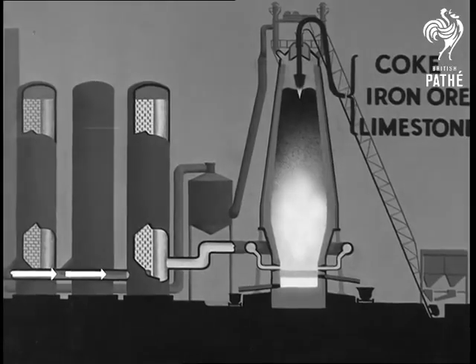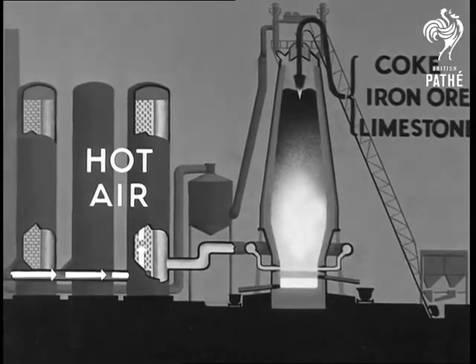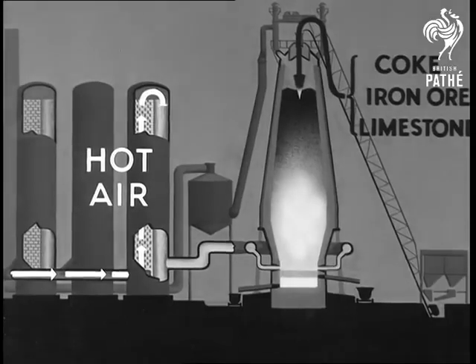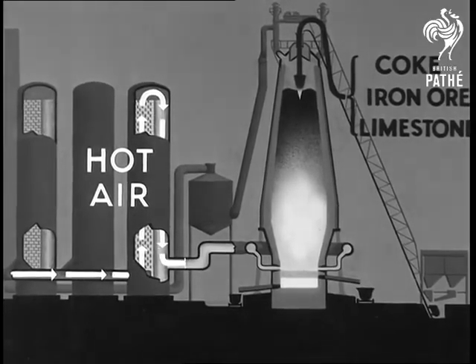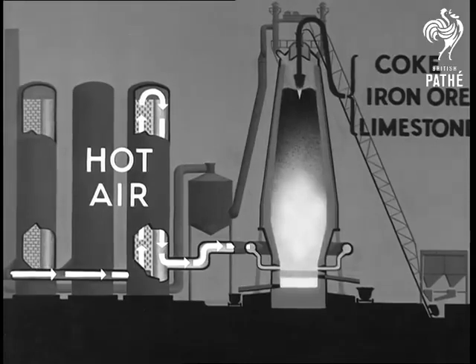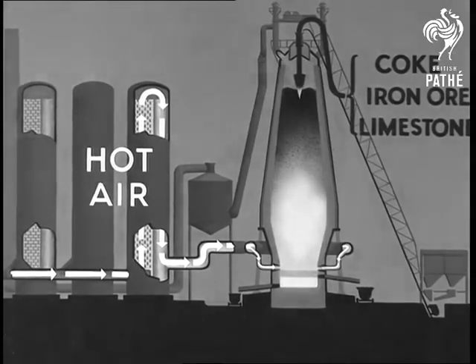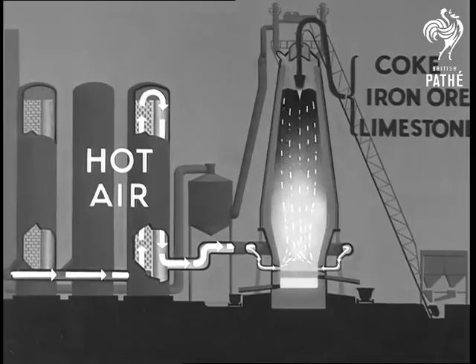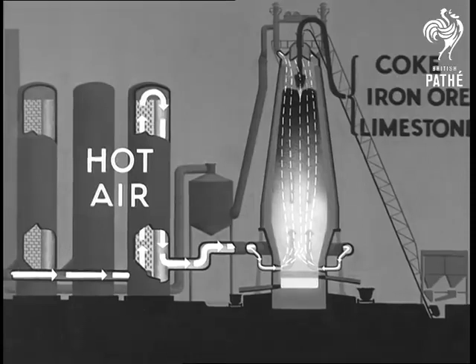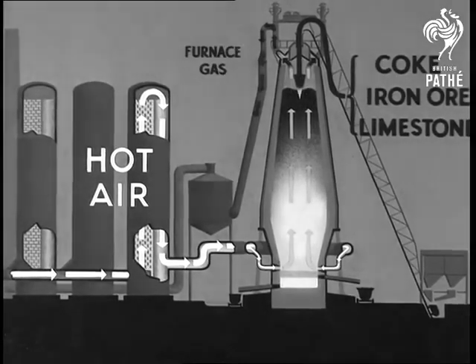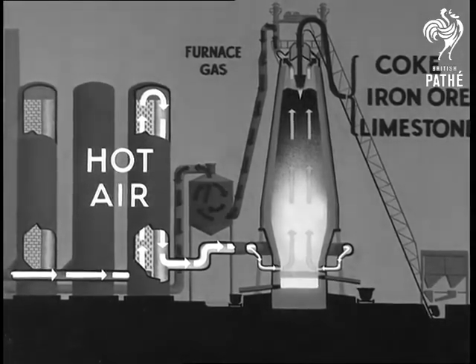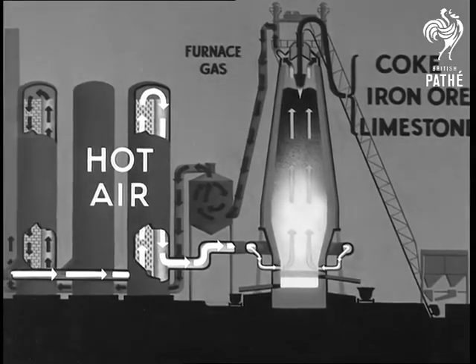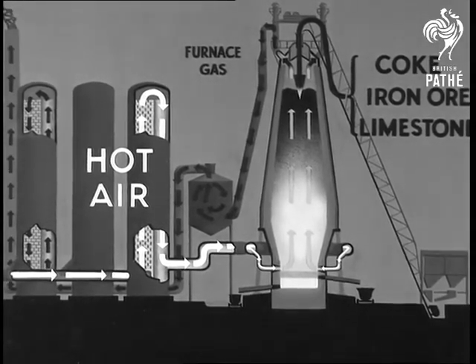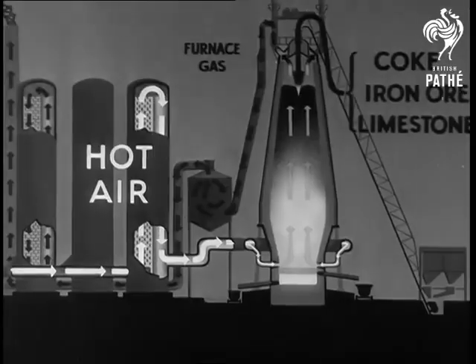A current of air forced into one of the stoves is made hot by a checkerwork of fire bricks already heated to about 1,000 degrees centigrade. This hot air passes into a bustle pipe encircling the lower part of the furnace, and then into the furnace via a series of smaller pipes called tuyeres. The gases released in smelting pass up through the furnace, out at the top, down into a dust catcher, and are burned in another stove where they heat up the brick checkerwork. Finally, the exhaust gases, containing no carbon monoxide, pass out into the atmosphere via the stack.